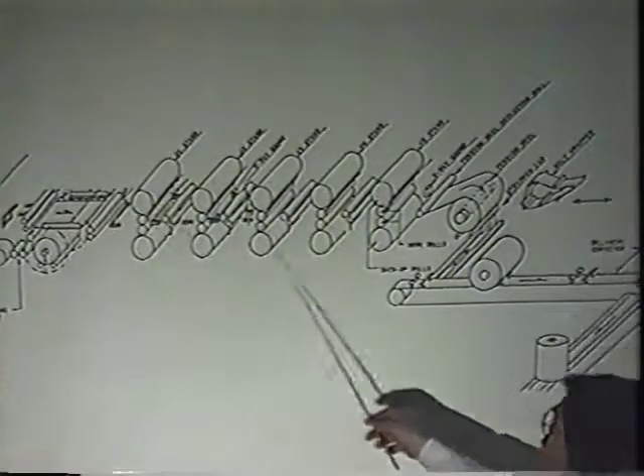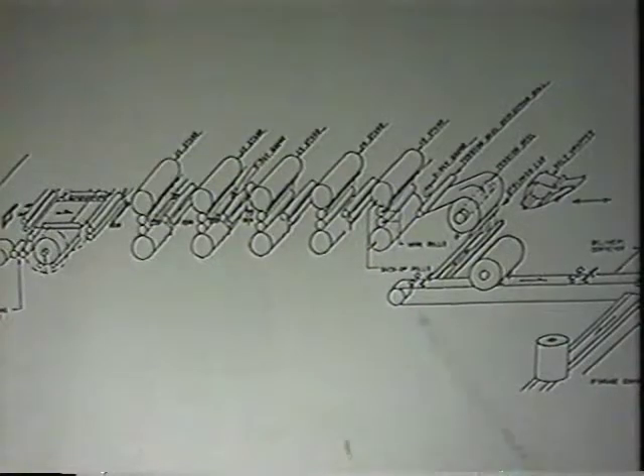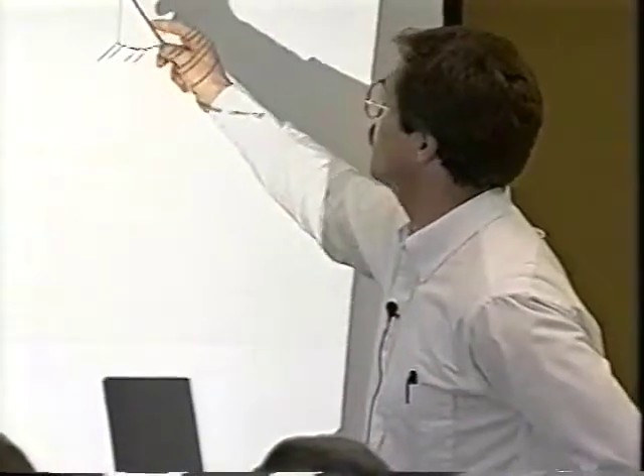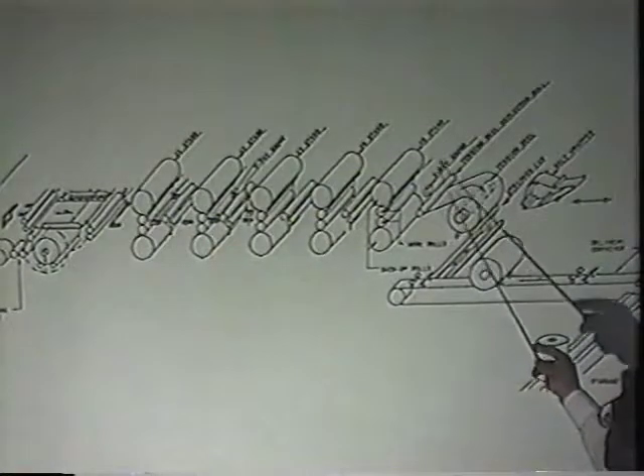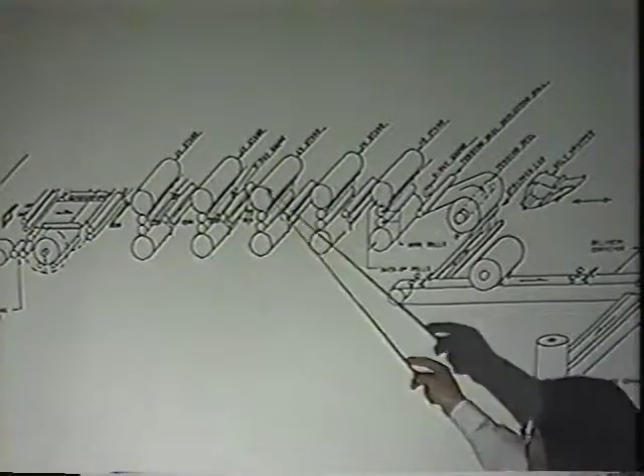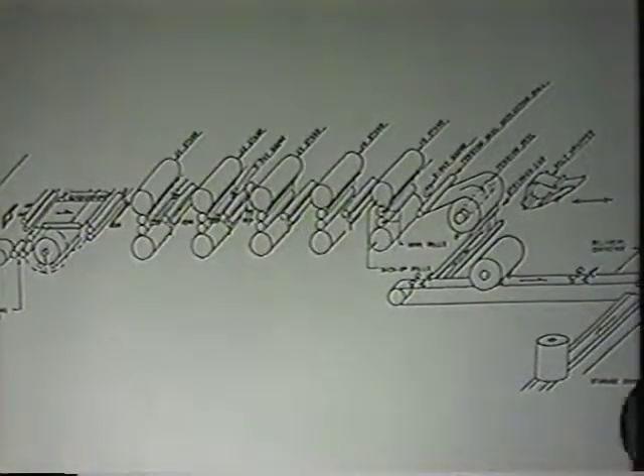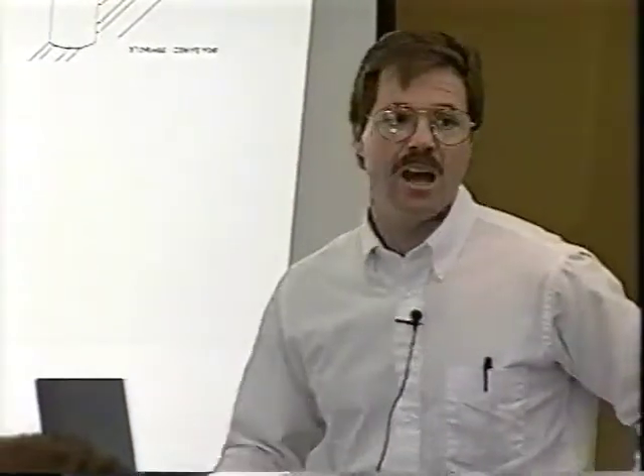Strip comes in one end, goes through each reduction stand, and comes out the exit end. It's just like you saw at the hot mill. We control the strip thickness with an X-ray gauge at center width. There's an X-ray gauge at the finish stand and one right here. The strip comes through, the X-ray reads how thick it is, and feeds it back to the computer. The computer adjusts the speeds, the roll gaps, the forces, the bending, etc. It's basically beyond the ability of a human to control the whole process and get an acceptable product out the back end. Elaborate process control scheme.